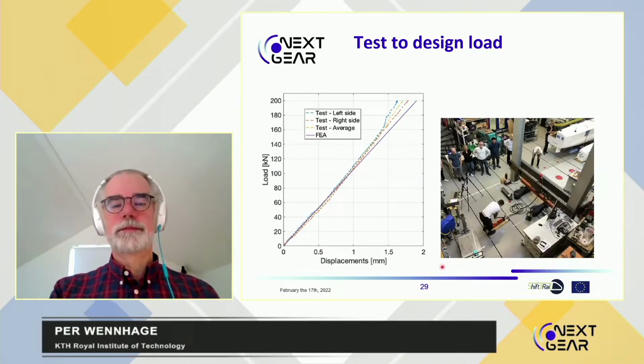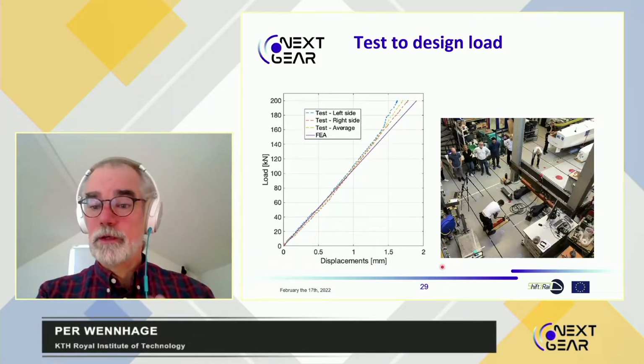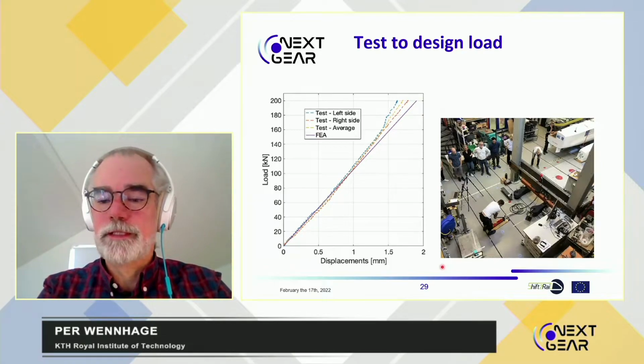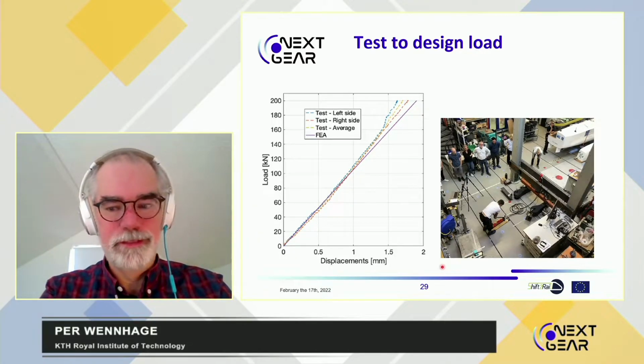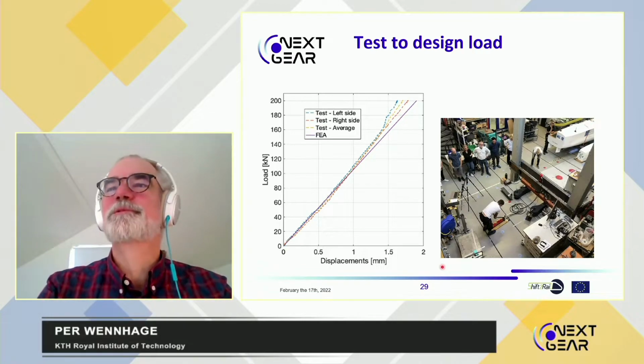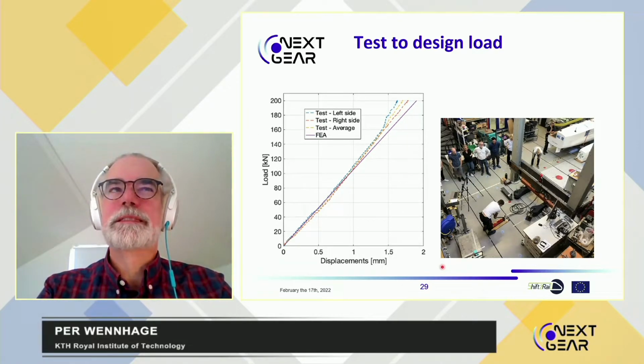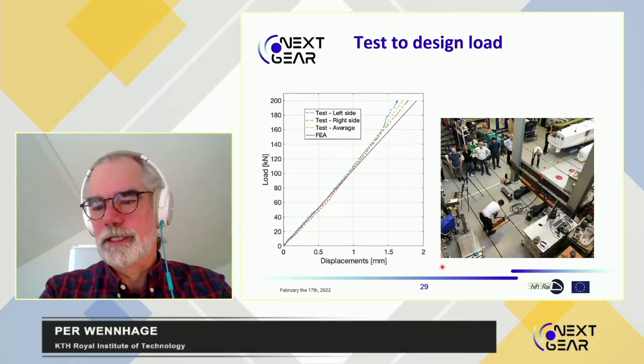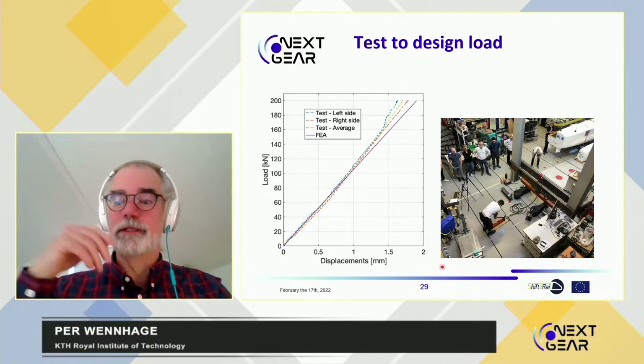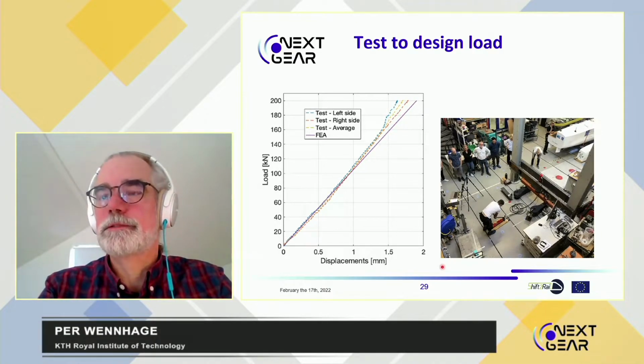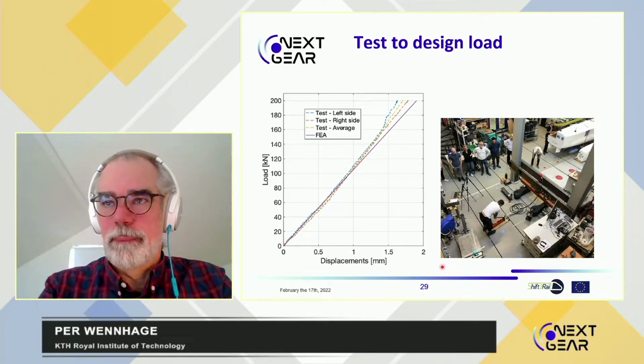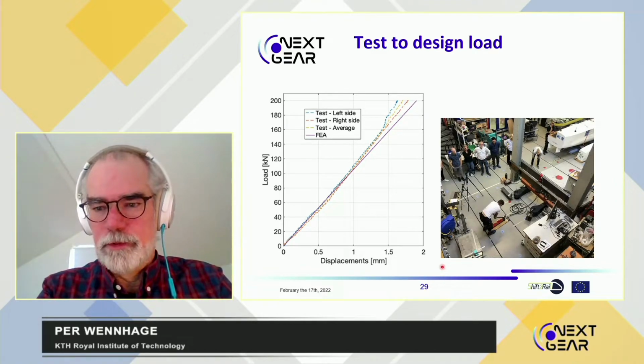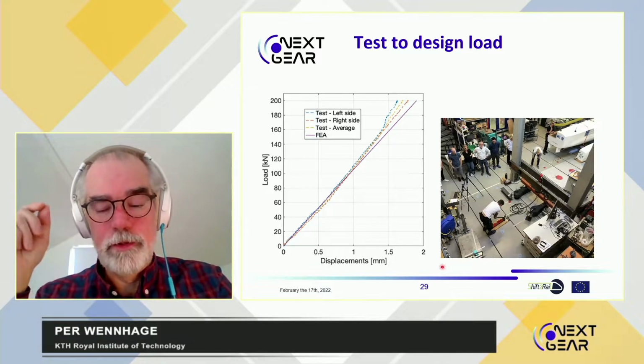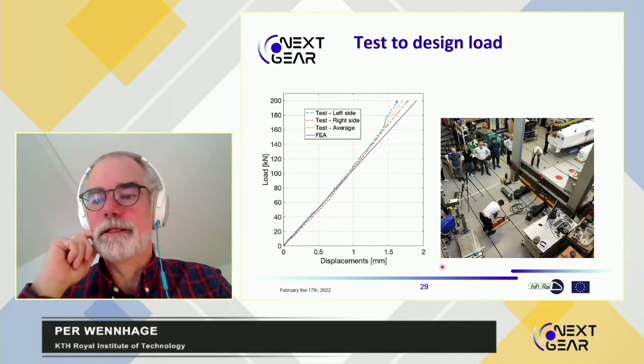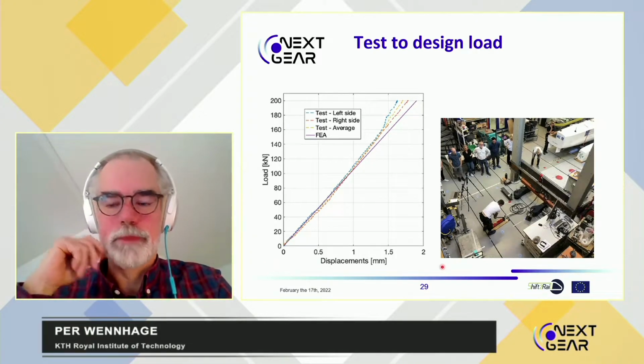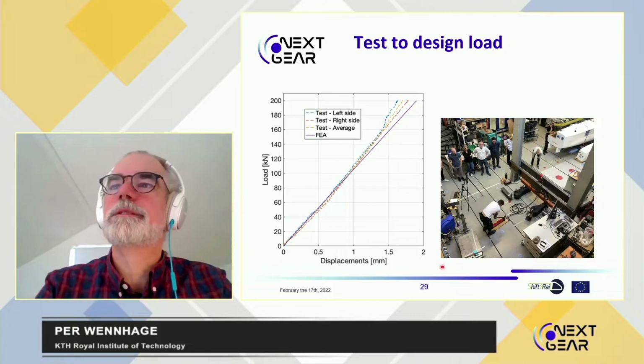The final test that we did was to load it in vertically to the design load. We did this last just to be sure that we didn't break anything, of course, before this. So we loaded it to a total load of 20 tons as if it was mounted on the vehicle, and this is the vertical compression case. You can sometimes hear when a composite structure is about to break that you can hear some cracking. And I didn't hear any cracking at all around this one. My hearing is quite good, actually, so I couldn't hear any cracking here.